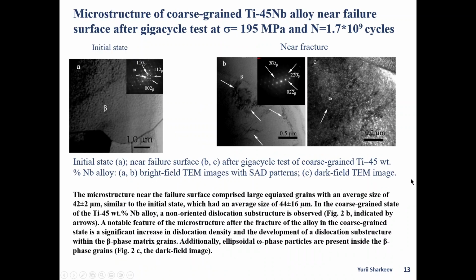The microstructure near the failure surface comprised large equiaxed grains with an average size of 42 micrometers, similar to the initial state, which had an average size of 44 micrometers. In the coarse grain state, titanium niobium alloy, a non-oriented dislocation substructure is observed. A notable feature of the microstructure after the fracture of the alloy in the coarse grain state is a significant increase in dislocation density and the development of a dislocation structure within the beta phase matrix grains. Additionally, ellipsoidal omega-phase particles are present inside the beta phase grains.